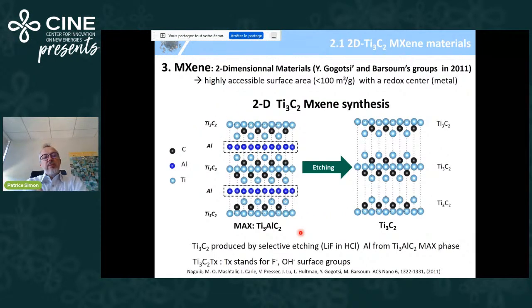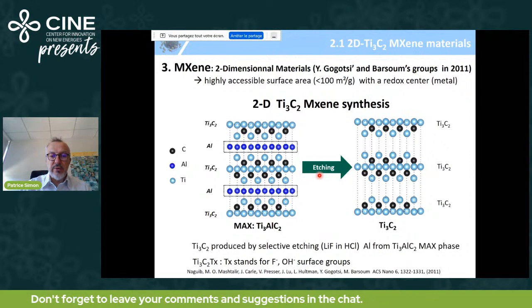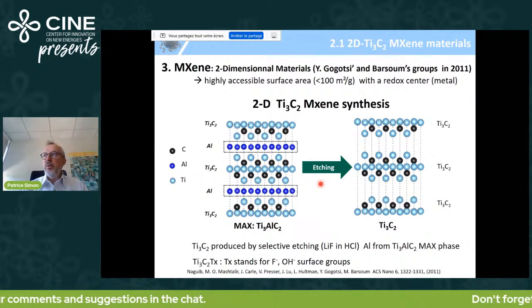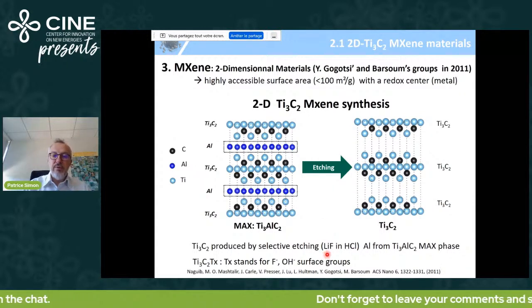And now I move to MXene after this introduction. Why MXene? Because MXenes are two-dimensional materials pioneered by Gogotsi and Barsoum's group, and these are 2D materials with highly accessible surface area. To prepare a MXene, you start from a MAX phase. One of the most popular is where M is titanium, A is aluminum, X is carbon. In these materials, X is carbon or nitrogen, M an early transition metal, and A a valence metal. So Ti3AlC2, you start from this material, and you etch it in hydrofluoric acid or a fluorine-containing acidic electrolyte, typically lithium fluoride in HCl.